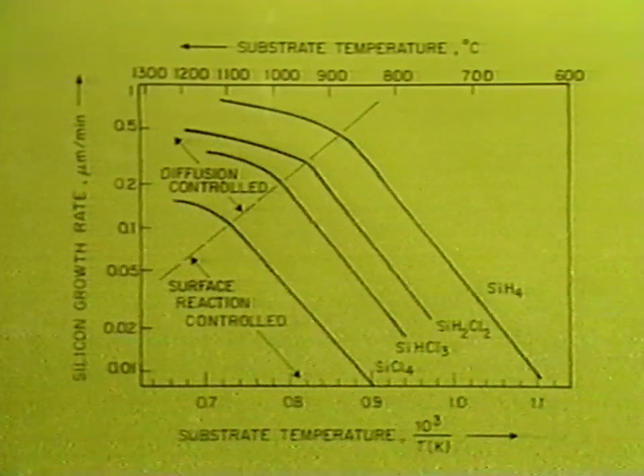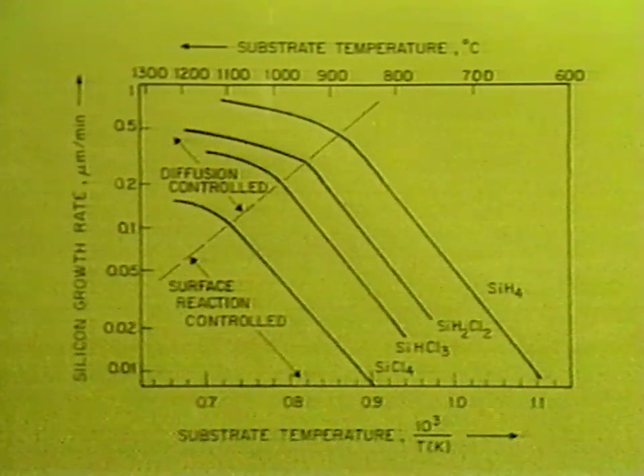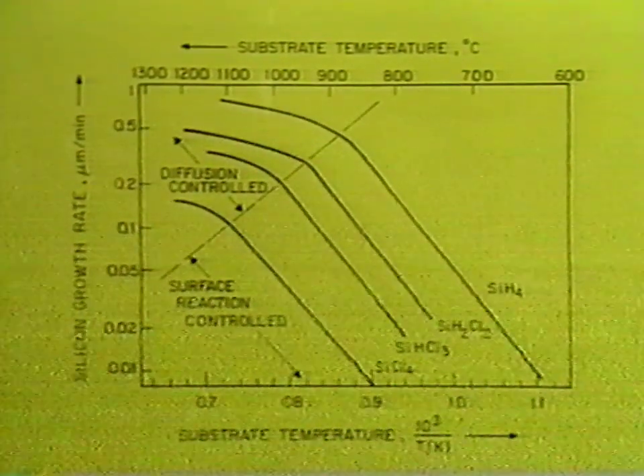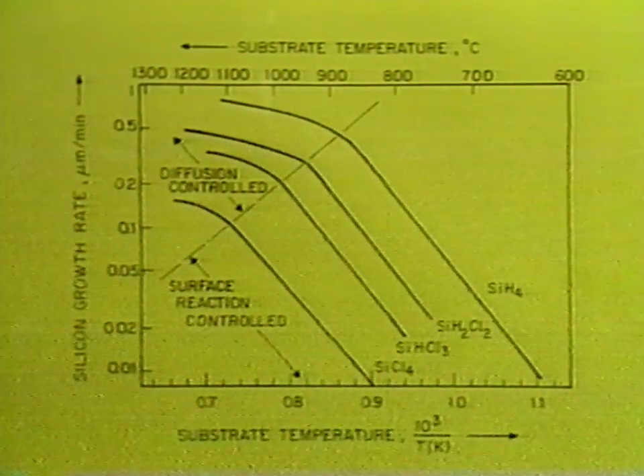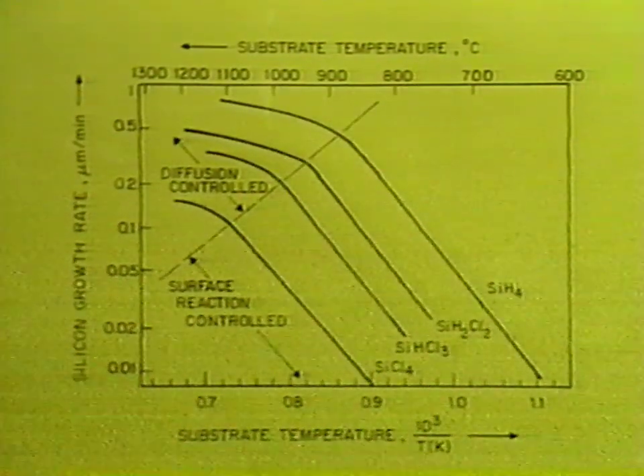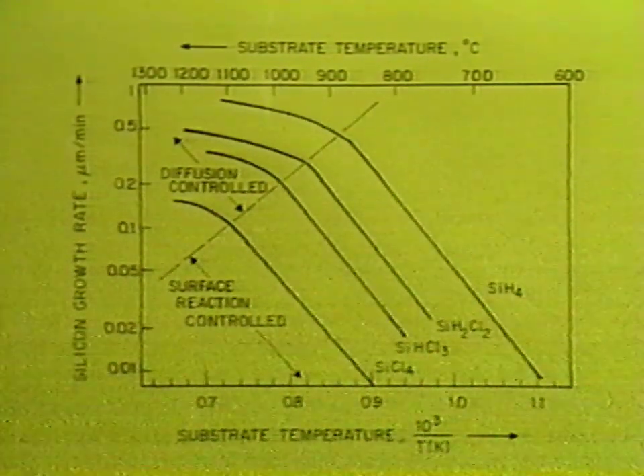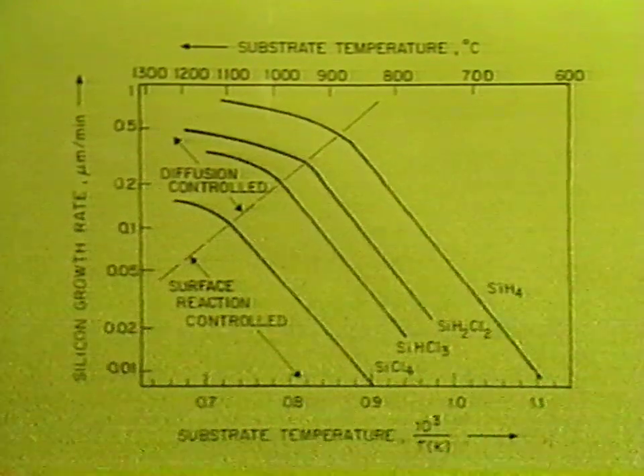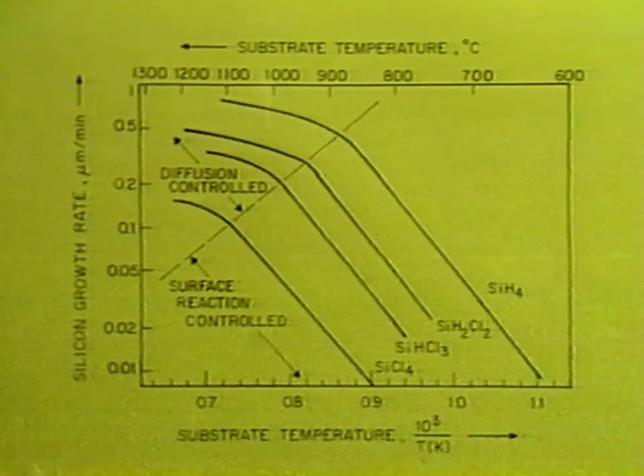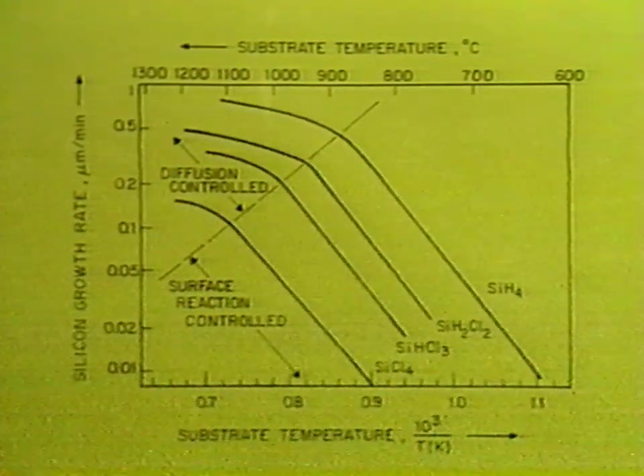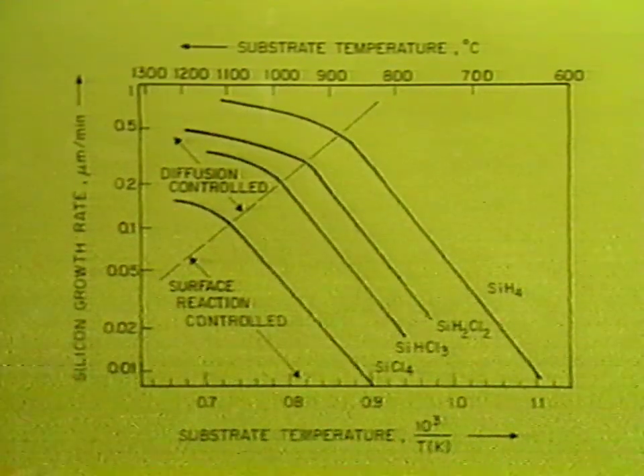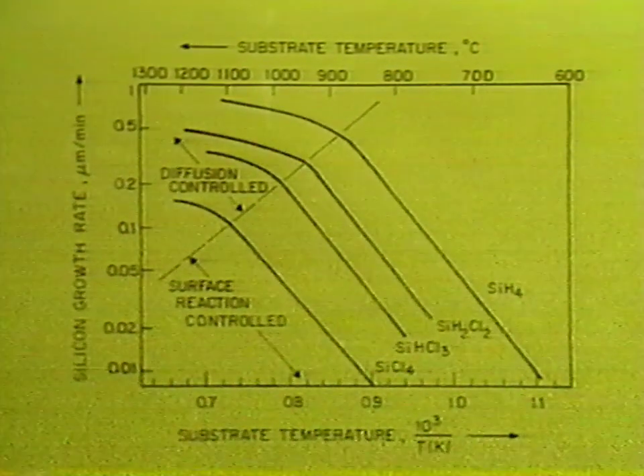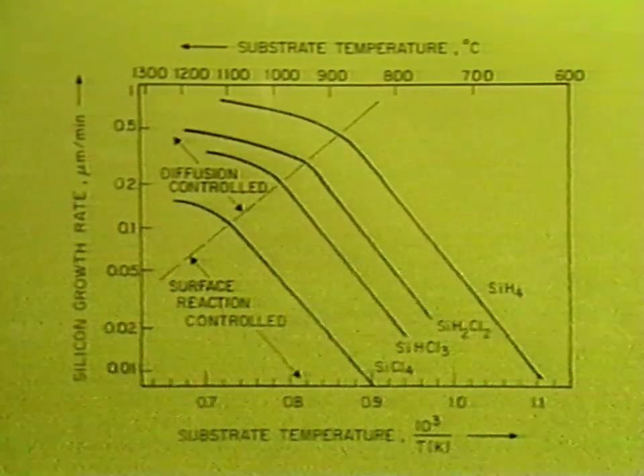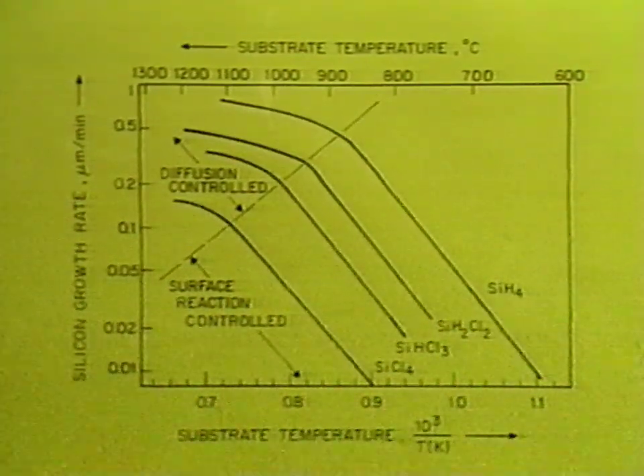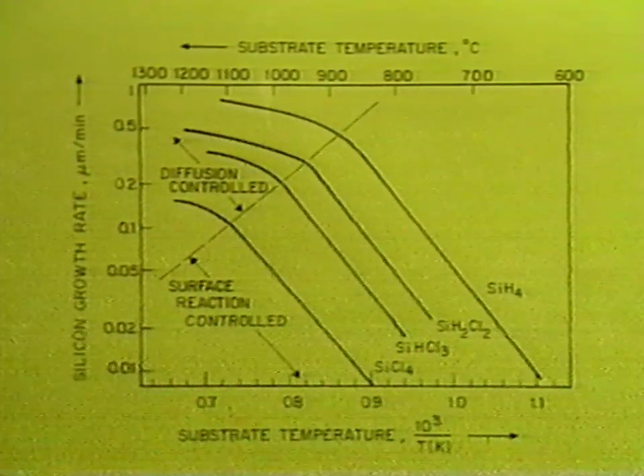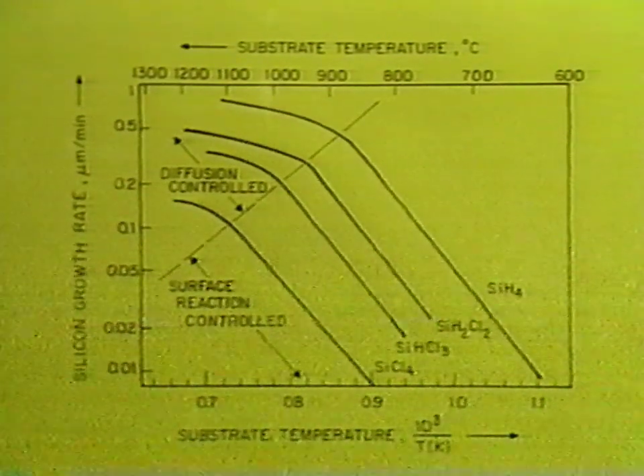This is a typical presentation of the type of reactions we are talking about here. We have the growth rate on the left side as a function of absolute temperature for the deposition of silicon from various source gases, silane on the top, and the various types of chlorosilanes. And you can see that, first of all, the absolute deposition rates vary, but the slopes are essentially very similar, meaning the activation energy also is very similar for each of these reactions.